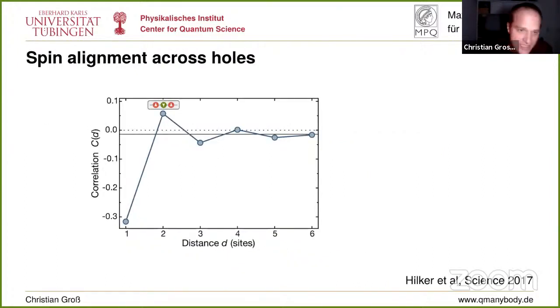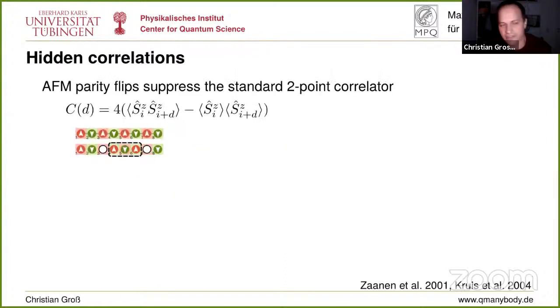We can study this. So let's now go to 3-point correlators. This is first the normal 2-point thing I have shown you before, but now we can measure the correlation selected on having a hole in the middle, and you see the correlation turns completely around, and we see actually the opposite sign of those spins if there's a hole in between. That's a very short distance measure, and I want to show you now that we can also get longer range correlations back if we use more complex correlators.